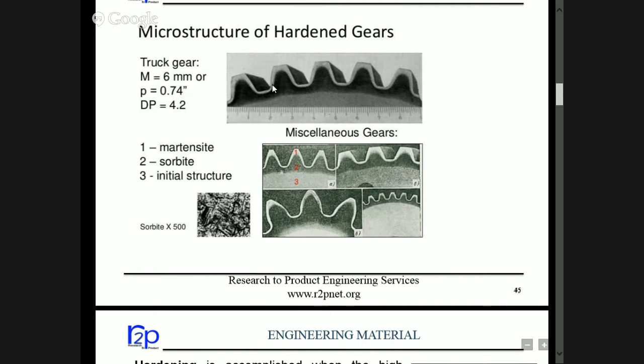So if you see in case of a geared component, here this white is the martensitic hard layer, and in between the structure is sorbite, and in the core it's the original structure, which is the soft one. So in case of a gear, the hardness desired is even in the root area, because the compressive stresses build up due to carburizing and quenching. They will also help against bending failure of the tooth at the root level.